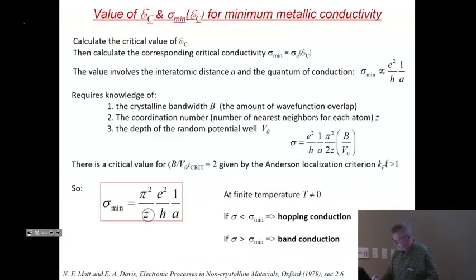And this, of course, with z equals 6, is 610 inverse ohm centimeter divided by a in angstrom. It's a classic test that you have to do for all your samples. Take a sample and measure the amount of ohms and convert that to this value.